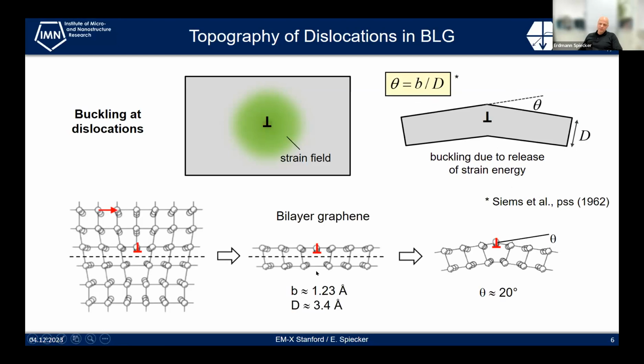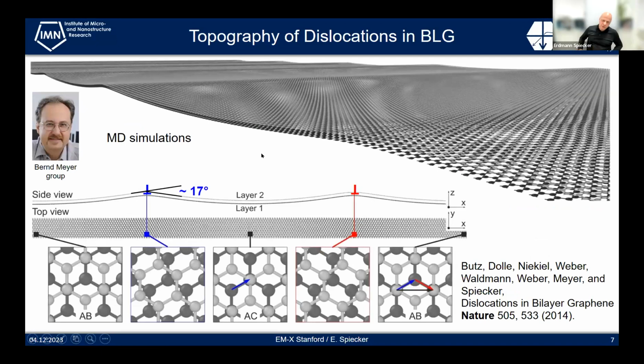If we now go to an extreme, and this is just an illustration of a bilayer graphene, and we assume that the thickness is only 3 angstrom or 3.4 angstrom, we would expect a buckling of 20 degrees. So a huge buckling because the sample is so thin. In fact, this is also what we observed and what we could show experimentally back then. But here I want to, just for illustration, show the MD simulation of my colleague Bernd Meyer. And you see here in a bird's eye view, the graphene with these dislocations, and at each edge dislocation, you have a buckle. And the side view shows that we actually have a buckling angle of 17 degrees, which is very close to what we would expect from this early formula.